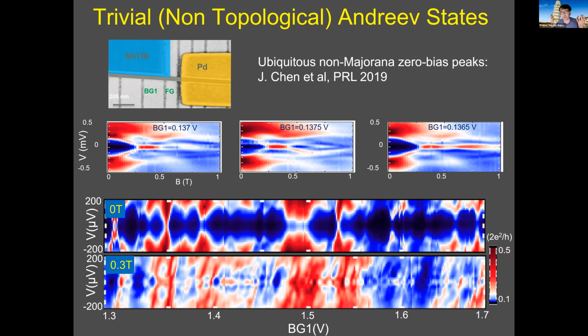Inside this soft gap, again, yes, the gap is soft, but you can see very clearly the peak inside the gap. Well, can you? In fact, it could also be a mishmash of several different peaks that come together near the zero bias, right? For example, in the middle panel, it looks like there's a state crossing, which is red, and then another one, which is white, displaced by a few hundred millitesla, and together they make it look like an oscillation, right?